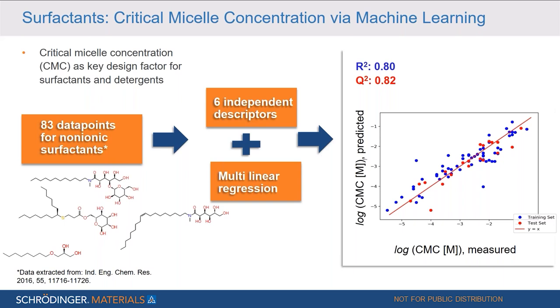And in this case, only 83 data points for non-ionic surfactants were used, together with 6 independent descriptors, and multiple linear regression was applied. And we can see here the results on the right-hand side. And we see that already with such a moderate size data set, we can get quite reasonable results. And so we can successfully apply QSPR approaches even though we have only a limited amount of data available.